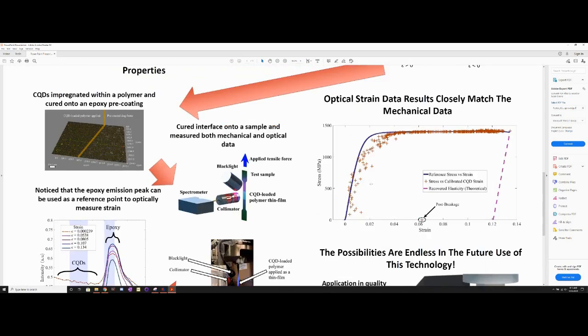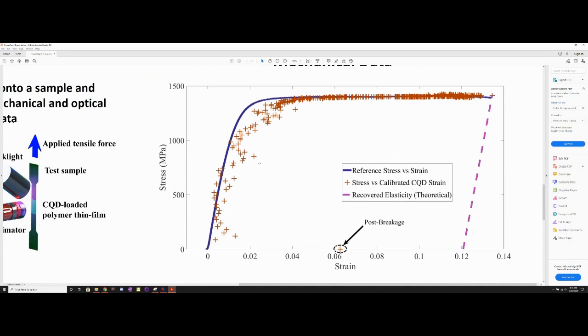At the end of it, you can get this beautiful stress strain curve here, comparing the optical to the mechanical, and it follows it very closely all the way till the end, which is failure. And the reason for all the deviation on the left side here is because the film is not over the entire dog bone itself, it's actually in a local area. Thus, it's going to be looking at a localized strain, not the overall that the mechanical can do.